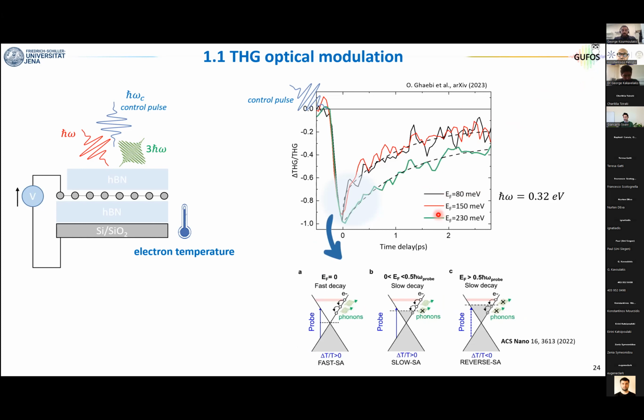And in particular, the main difference is not in the slow component that is always there, but it's in this initial fast component that basically disappears as we go to large values of the gate voltage. And now we know why this is happening. This is again a work that we did with Giulio Cerullo. And the idea is the following. When you generate hot electrons, that means electrons that lie at high energy in the Dirac cone, if you want to dissipate energy to the lattice, you have to decay into the Dirac cone and emit an optical phonon.